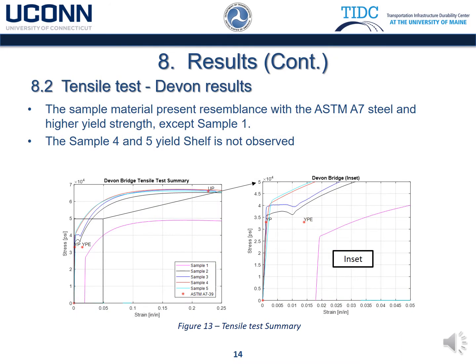Tensile test, Devon Bridge. As we can see on the left side of figure 13, the tested material presents resemblance with the ASTM A7 steel, except sample 1, which showed lower values. The right side of figure 13 shows the inset of the elastic region, and we can observe that sample 4 and sample 5 don't show the yield shelf.